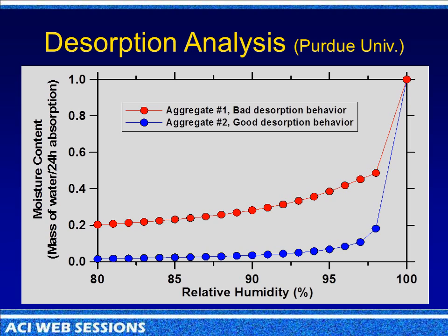Now, what you want is you want the moisture to come out with a relatively high humidity inside it. And so about up to 90%, you want this moisture to be coming out because that's when the cement really needs it. The cement or the supplementary cementitious materials.